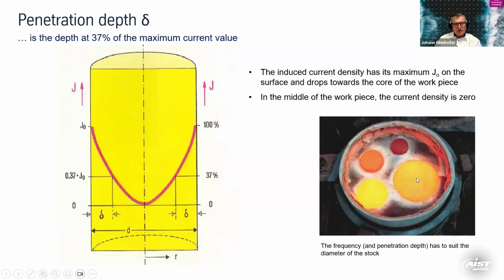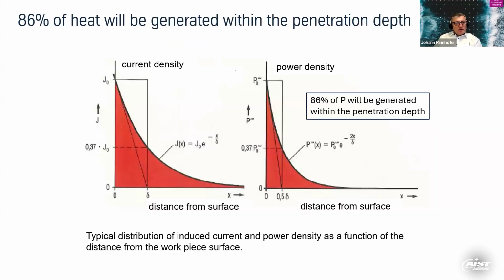You see there are different pieces. The red one is very bad. The yellow one is optimum. The other ones are in the middle. Because the power is current squared times resistance, 86% of the heat will be generated within the penetration depth. This is the message here.